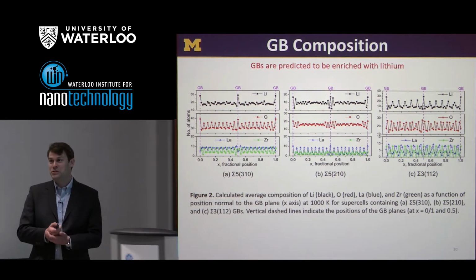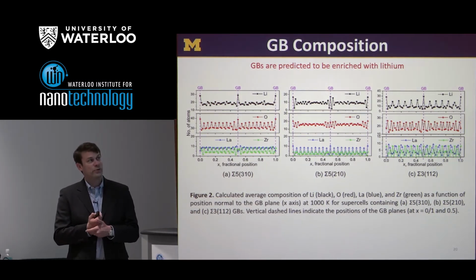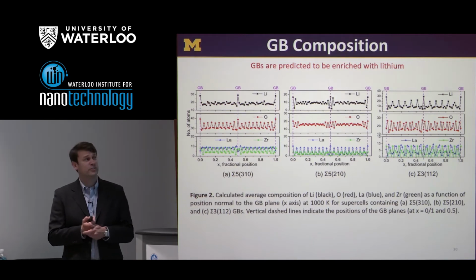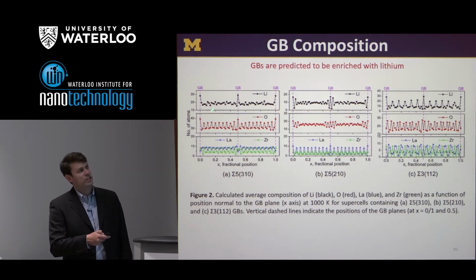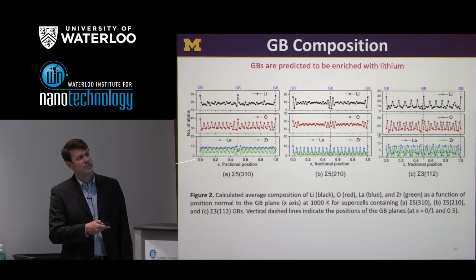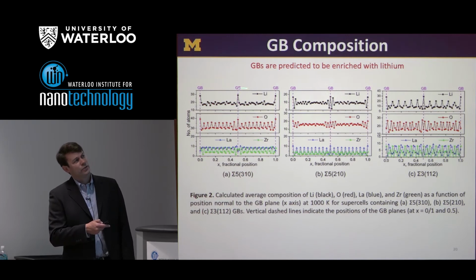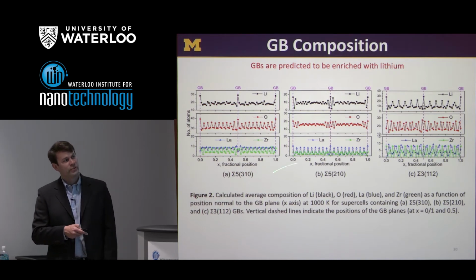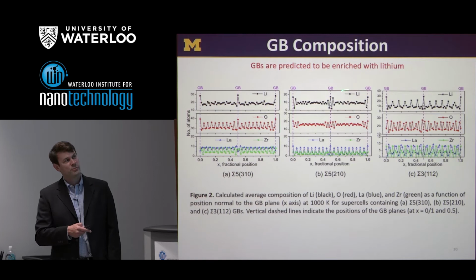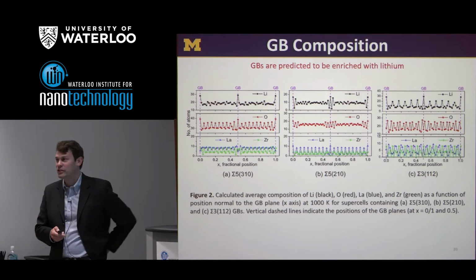So the first thing we want to know is, well, how does the composition of the grain boundary compare to the bulk composition? And so what we do is we take a planar average of, say, the lithium concentration, the oxygen concentration, or the lanthanum and zirconium concentration as a function of position in the cell. And remember, there's a grain boundary in the middle, there's one on the edges. And so if we look just at the lithium at the top, for these three different boundaries, we see there's a peak in lithium concentration in the boundary plane.